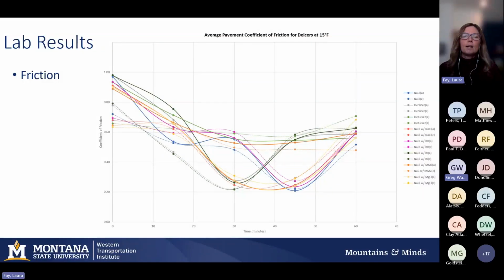remained level. And then after 30 minutes, there was a split again in which products either remained at higher friction values or had a drop in friction. What's interesting is that the products that had high friction at 30 minutes, at 45 minutes had a significant drop in friction, and the opposite was true. The products that had low friction at 30 minutes had an improvement in friction by 45. And then after the hour, almost all the values coalesced around 0.6. So again, a good, reasonable friction value.